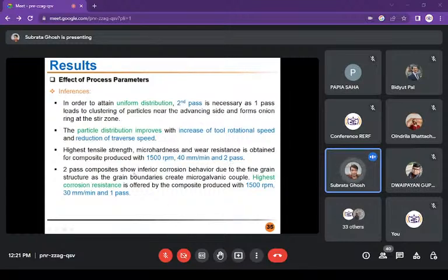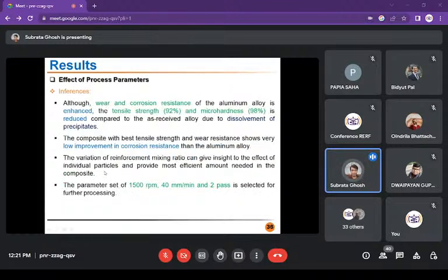The second pass composite shows inferior corrosion behavior due to the fine grain structure, as the grain boundaries create micro galvanic couples. So the second pass is showing better results in all respects because of the overall distribution of the reinforcement particles in the matrix. And here you can see that the wear and corrosion resistance of the aluminum alloy is enhanced.